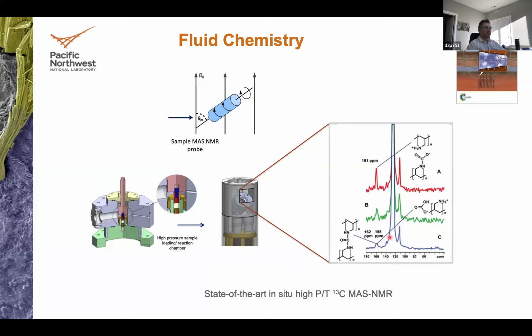If in some cases you have some dehydration process, you form an actual non-reversible link, which is a urea linkage. This is a typical urea bond that you see in urine, for example. But most of the reaction takes place around the ammonium carbamate, and then when pressurizing or reducing the temperature, you go back to the amine and the CO2 free.